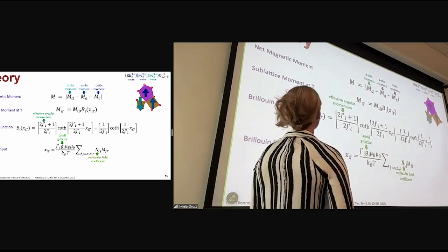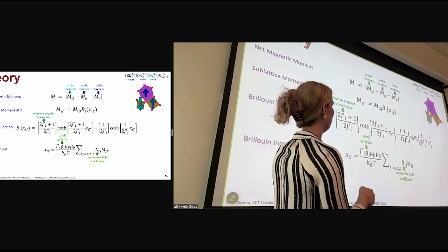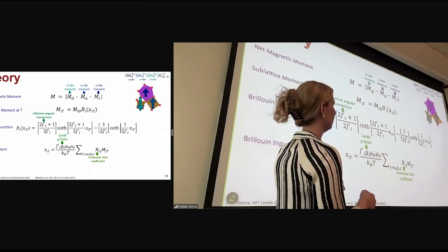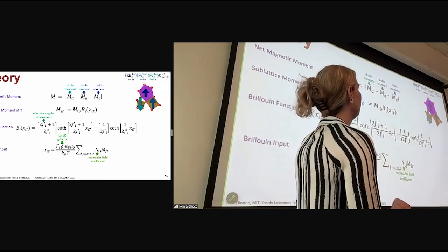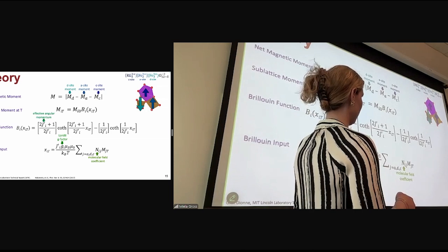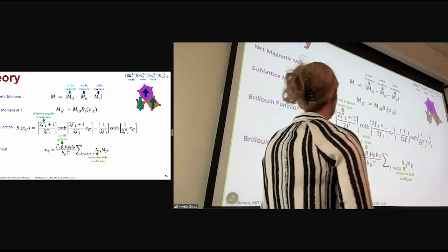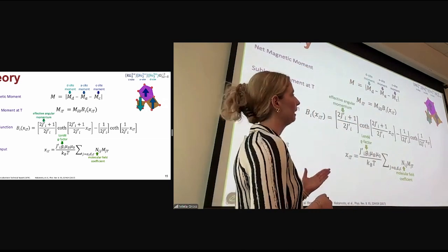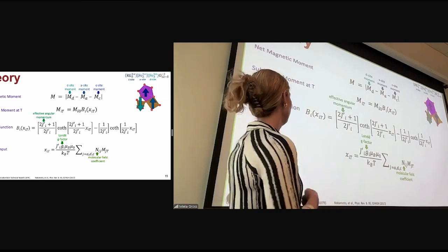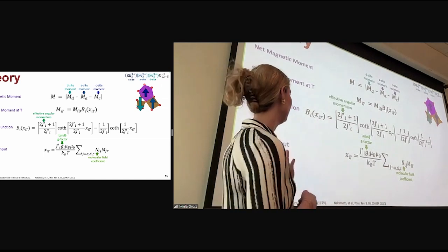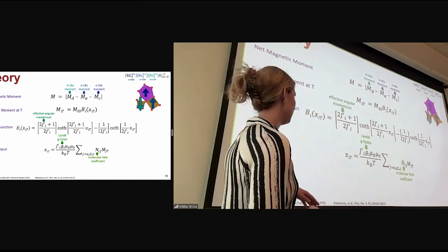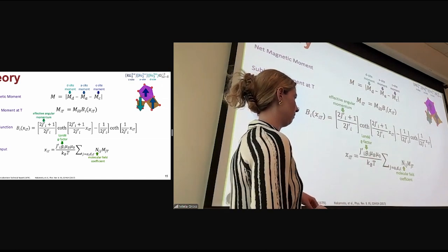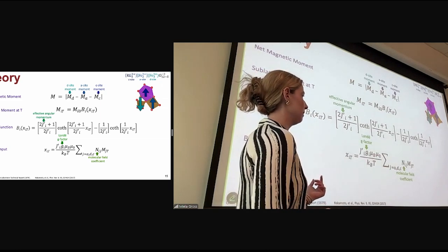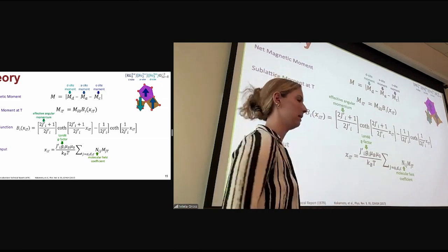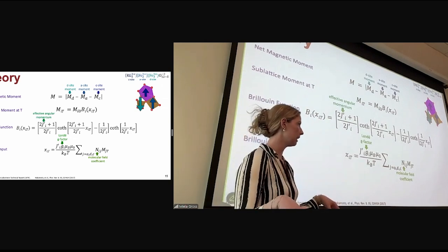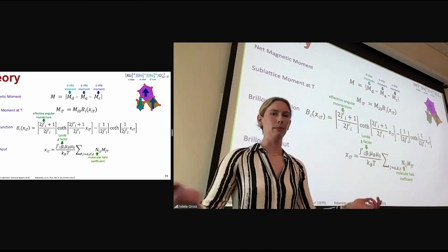So as I mentioned previously, the net magnetic moment of our garnet is a combination of the moments of each sublattice here. And I added a picture in the upper right-hand corner to remind you all what each of those sublattices are and their site occupancy. Each sublattice can be broken down into their 0 temperature magnetic moment and a Brillouin function. If you don't remember what that is, I have it listed here. It takes in this input X here that has a temperature dependence, as well as the properties of whatever magnetic ion you have. And then this molecular field coefficient here describes the inter and intra sublattice coupling between that site and itself or neighboring sites.